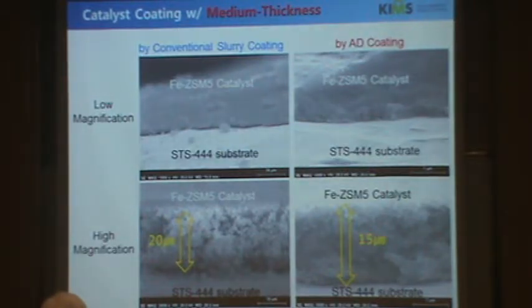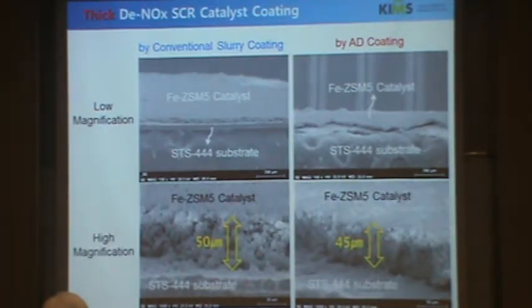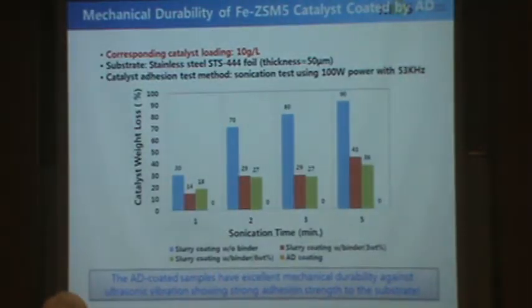This one is medium thickness, like 20 micrometers. It looks similar, the conventional coating and the special coating. We did 50 micrometers using this technology. So regardless of the thickness, we made a similar microstructure using this technology. And then we tested adhesion using the conventional ultrasonic test. We put the samples in the ultrasonic cleaner and vibrated them, and we checked the rate of loss after drying the sample.